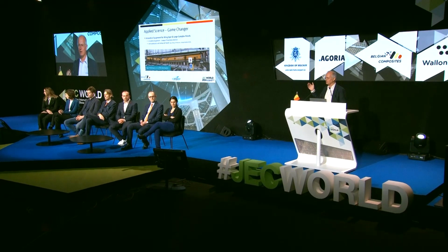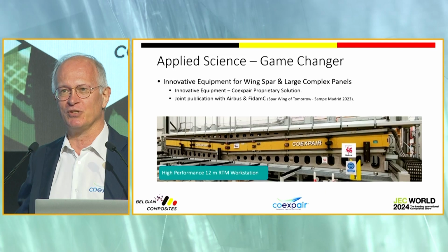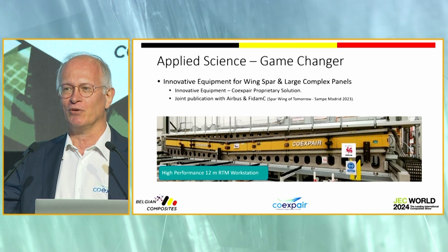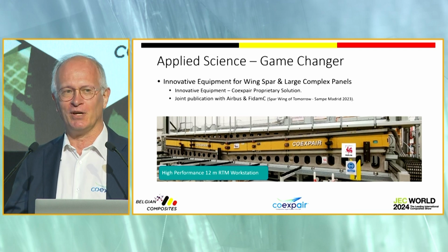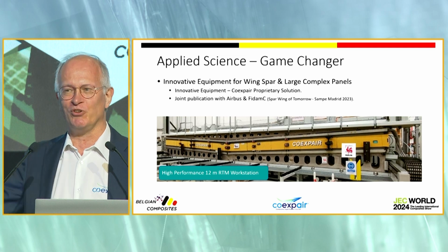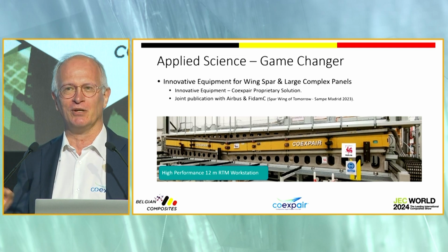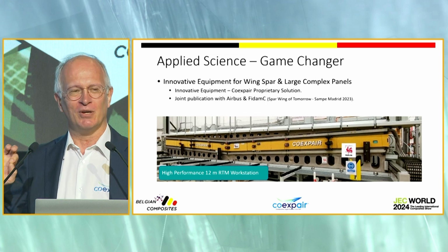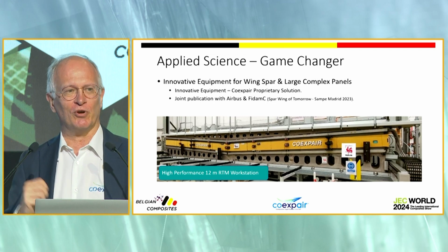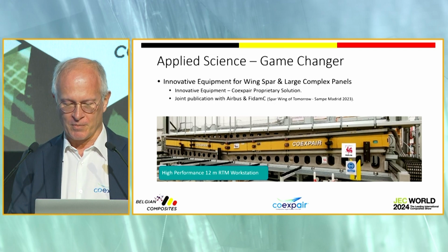So we made a 12-meter long mold in aluminum with a junction in the middle, but with very high vacuum. So we just inject from one inlet, one outlet, and we get the part. Very simple process, very basic philosophy. It was published at SAMPE Madrid 2023, using aluminum mold. It just scales up. We follow the size of the part.